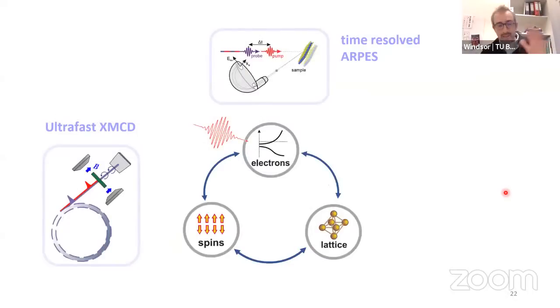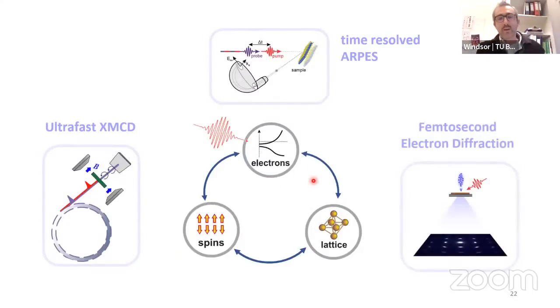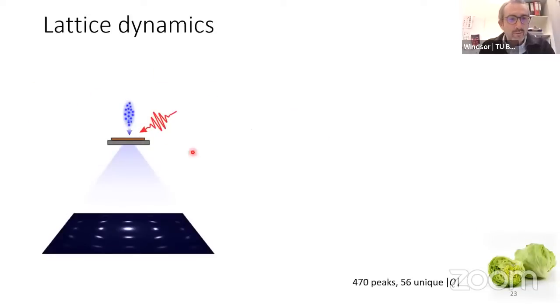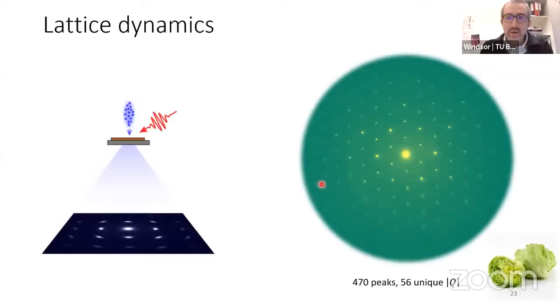So the last experiment here in our FAM collection will be an ultrafast electron diffraction experiment, shown cartoonishly here. And so what we have, if you look over here, is a femtosecond electron pulse and a laser pulse, both exciting the sample. The electron pulse passes through in transmission. It's the same kind of sample as I just showed for XMCD. And we get a diffraction pattern as shown here. This is a diffraction pattern from FGT.